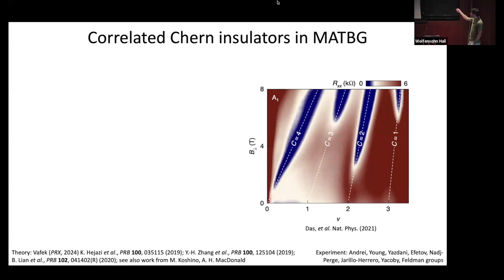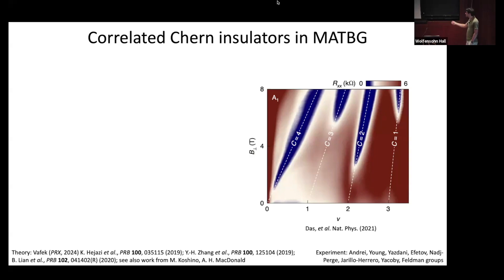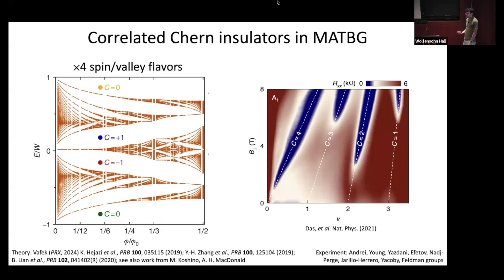These Hofstadter states have non-zero Chern numbers, meaning that when your Fermi level sits within one of these gaps between Hofstadter subbands, you get a sloped feature as a function of magnetic field and carrier density. In magic-angle twisted bilayer graphene, with flat bands, this entire Hofstadter spectrum has a very small energy window, so correlation effects dominate. What has been observed in many samples is Chern insulators appearing at some finite magnetic field — zeros in Rxx that are sloped, seen by many groups.